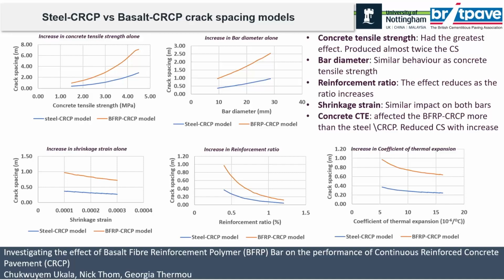So you see, it started with a huge difference, and it became closer towards the end, which gives us the idea that to get the kind of crack spacing we need when we use steel, we have to increase the reinforcement ratio of the basalt bar. But the more we increase it, the less the effect of it, compared to having a steel CRCP.